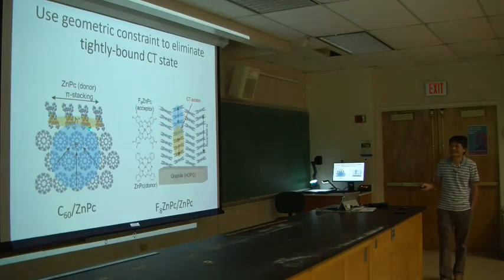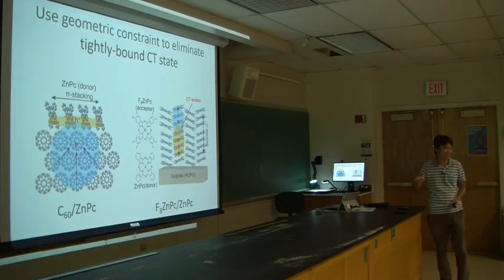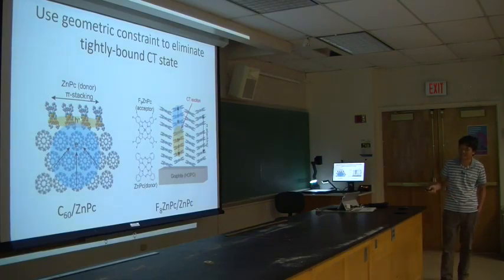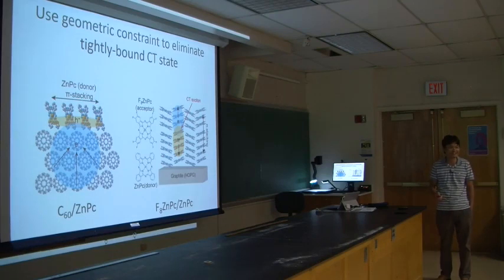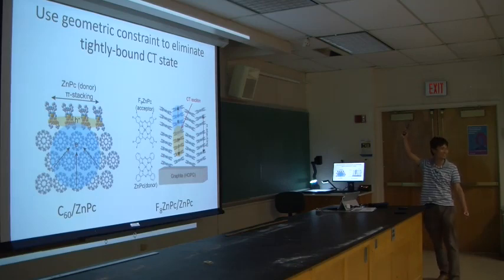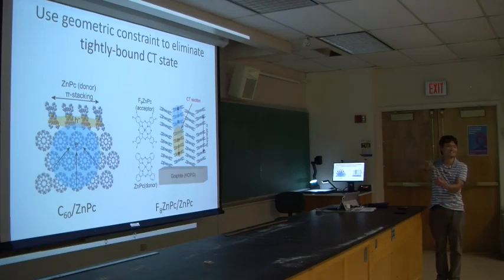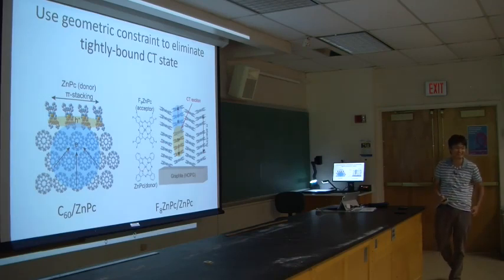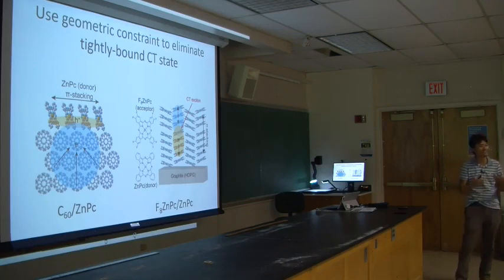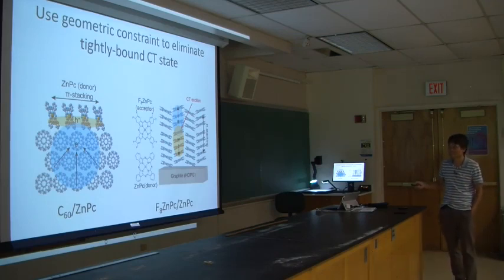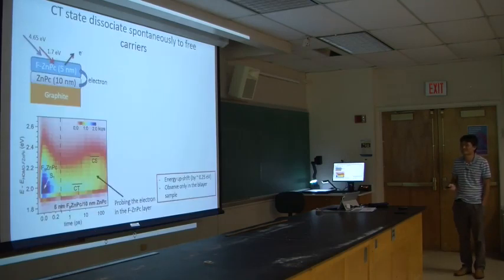So in the earlier interface, we have this hole basically delocalized parallel to the interface. So even though it's delocalized, the distance is still quite close to the electron, right? So we thought, can we change the stacking of this orbital a little bit so we can have this hole and electron delocalized in different directions, right? In that way, if this state can be delocalized, then automatically you force the spatial distance between them farther away from each other, right? So you weaken the exciton binding. So what we thought is you probably could generate free carriers easily with this kind of structure. So that's why we do this experiment here.